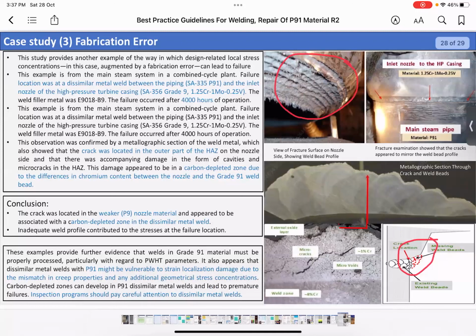It was concluded that P91 material might be vulnerable to strain localization damage due to the mismatch in the creep properties and any additional geometrical stress concentration. And we should always have a good inspection program for all dissimilar weld joints, and in particular the P91 dissimilar joints having P91 material.